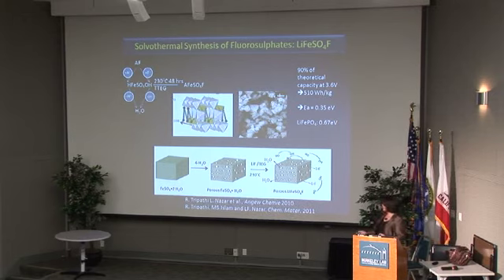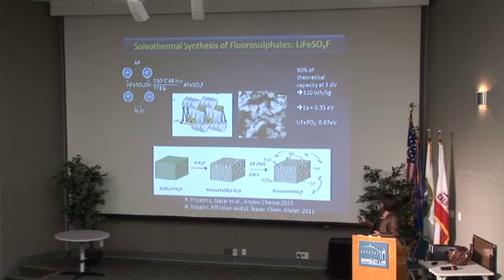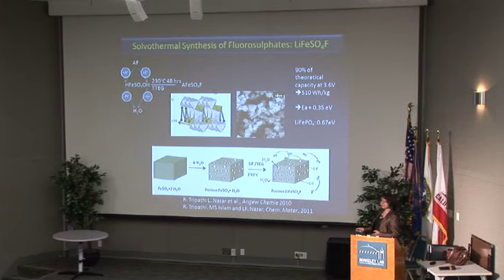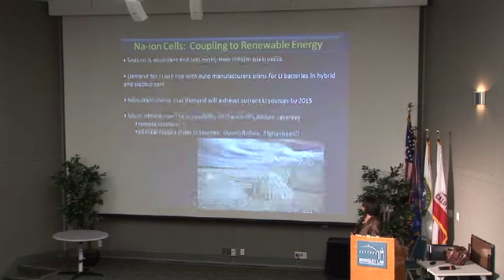We've also done modeling studies, which are reported in this Chemistry of Materials paper, together with Saiful Islam at Bath, and we've learned that the activation energy for ion transport is about half of that of the olivine. So not only does it have three-dimensional transport, it also has a much lower activation energy for ion hopping. And the point is that you can't make this material under normal solid-state circumstances. It decomposes before the kinetics will actually allow it to form.